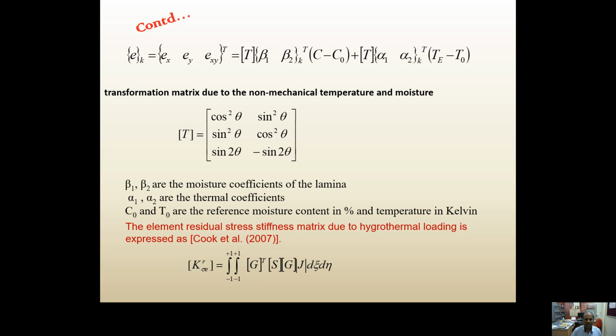In this slide, beta 1, beta 2 are the moisture coefficients of the lamina. Alpha 1, alpha 2 are the thermal coefficients dealing with the temperature of the specimen. C0 and T0 are the reference moisture percentage and temperature in Kelvin. The element residual stress stiffness matrix due to hygrothermal loading is expressed in line with Cook et al. for mechanical loading, and this is G transpose S G, modulus of Jacobian, d xi d eta.